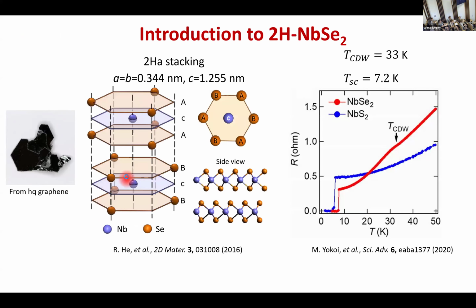So, niobium diselenide has this single crystal with a hexagonal shape. When you look at this crystal, it's called 2HA stacking. There are typically two different stackings, 2HA and 2HB. 2HA means basically when you look from the side view, the niobium atom aligns with the niobium atom in the other layer. So this is the kind of stacking. But you can see that the orientation of this selenium layer is different from the other one. So within a single layer, it actually breaks the inversion symmetry. So you don't have the central symmetry within a single layer.